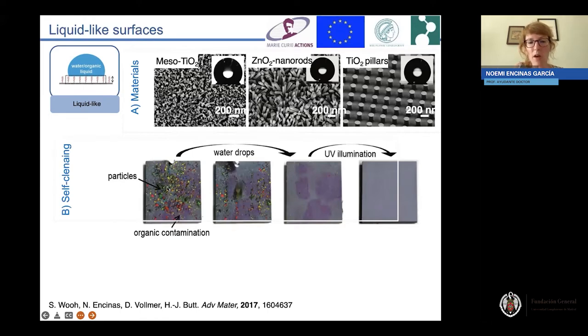properties. So on the macroscopic scale, if we had dust particles, in this case it was chalk, just by applying water droplets, due to the really high mobility of the water droplets, the particles were just removed from the surface. And also, if we had any type of organic contamination, just by illumination with UV light, due to the photocatalytic activity of the surface, we could remove it.